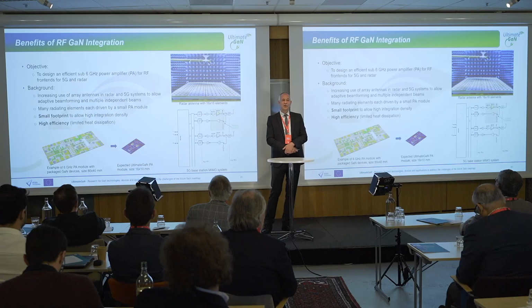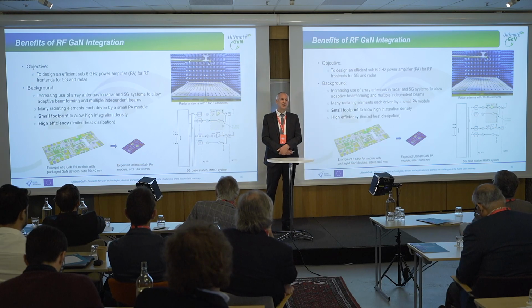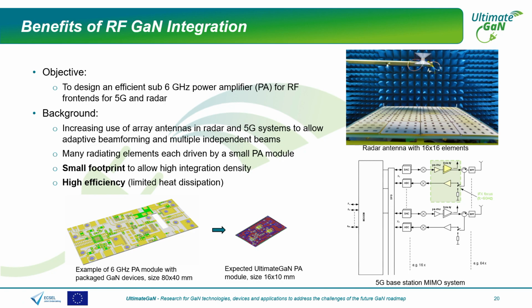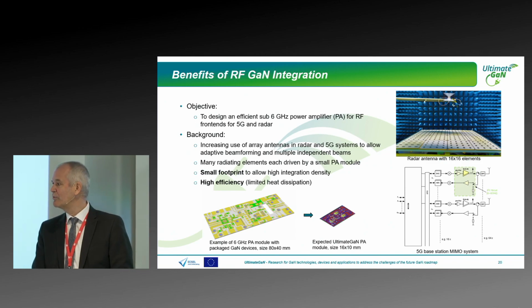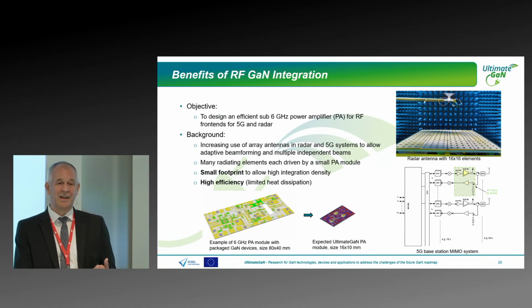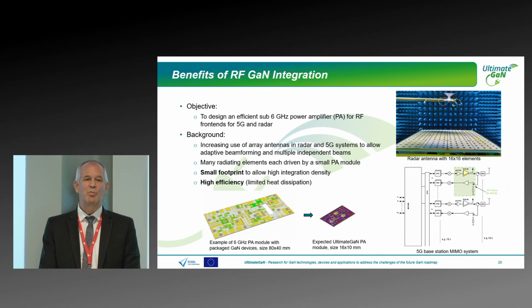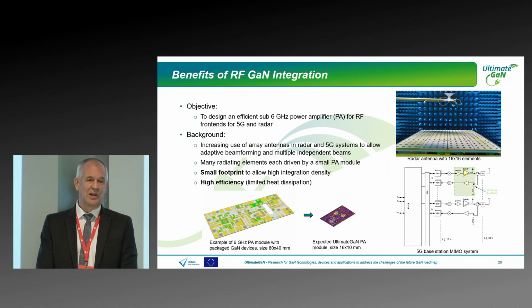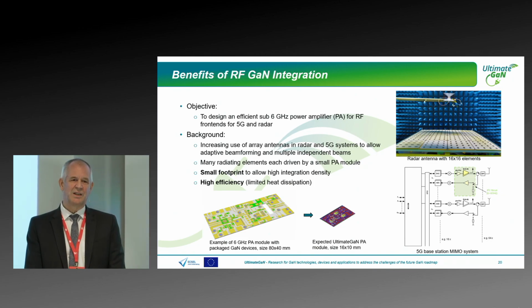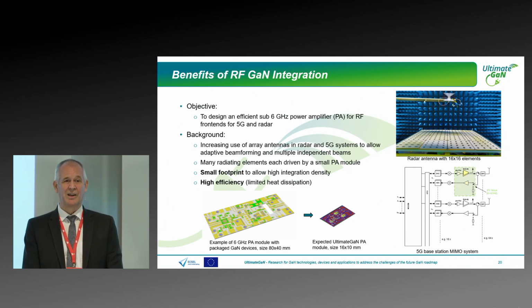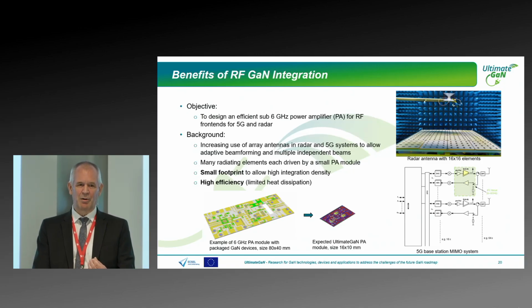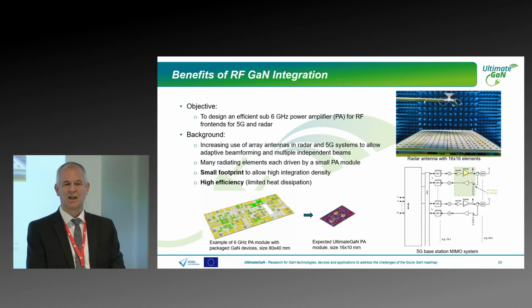So one thing we also did in this project is radio frequency gallium nitride power switches on silicon. Because for radio frequency it is very clear, it's GaN on SiC. It works, it's fine, and if you look into space or something like this, everybody will pay, nobody cares. If you look into 5G and the rollout of 5G, price matters. And GaN on silicon, radio frequency GaN on silicon, can be much cheaper than GaN on silicon carbide. And in this project, we demonstrated that we come close to the same properties of GaN on silicon carbide. And here it was not to be better than GaN on silicon carbide, but we are very, very close and ready for 5G, and I see a rollout.